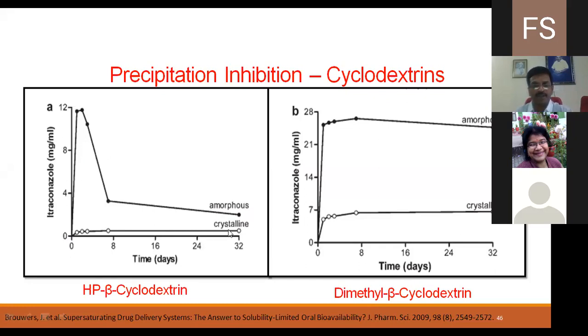And when compared to the crystalline compound without the cyclodextrin, we can see the HP beta cyclodextrin effect. So supersaturation effect is seen, and it is to some extent. But when compared with dimethyl beta cyclodextrin, complexation efficiency is significantly increased. The result is that the level of supersaturation is higher, but it generated a metastable solution, which is stable for a long time.